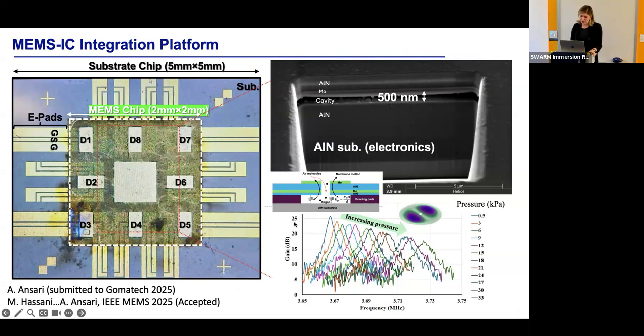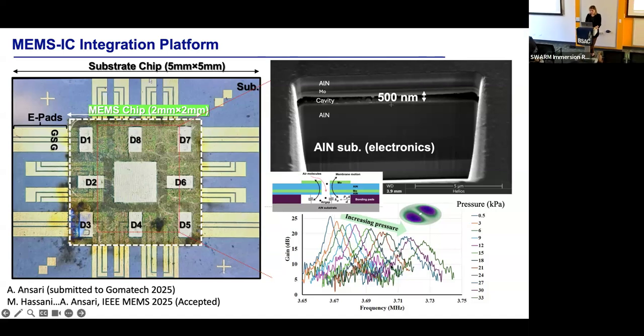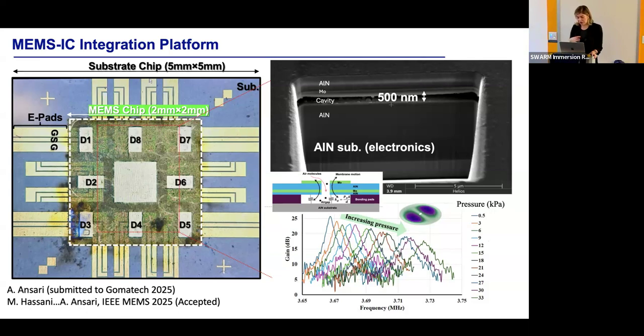Because the way that the pressure sensor works is a little different than static pressure sensors and even damping-based resonant pressure sensors. So here what happens is that when the pressure in the environment changes while your membrane is resonating, the gas that is trapped in this very thin cavity will exert a force, which modulates the stiffness of the membrane, and therefore your resonant frequency shifts. So as the pressure is going up, the frequency is actually increasing. So your membrane is stiffening instead of softening at higher pressure levels. And this can allow you to read out the pressure outside with a high sensitivity using this frequency shift detection method.